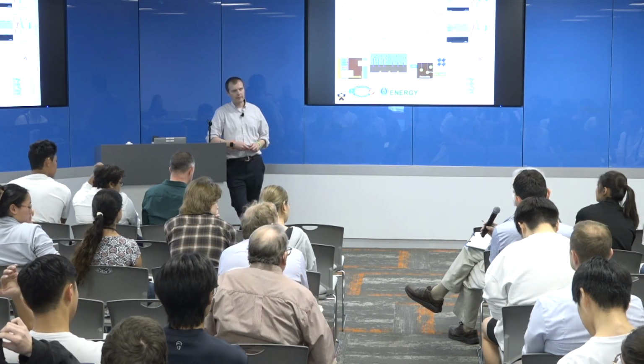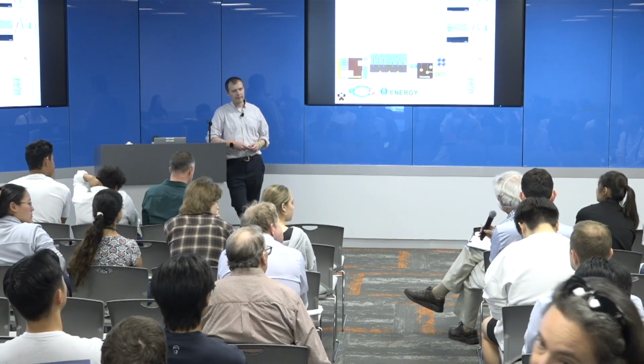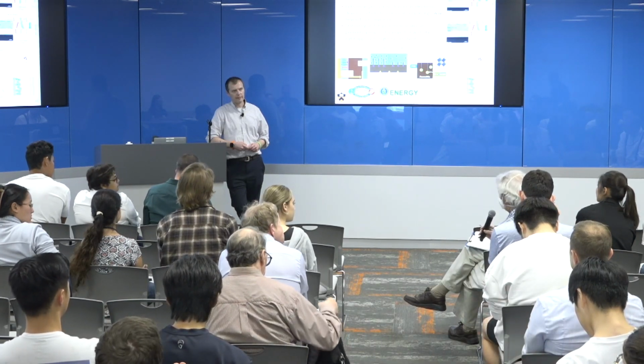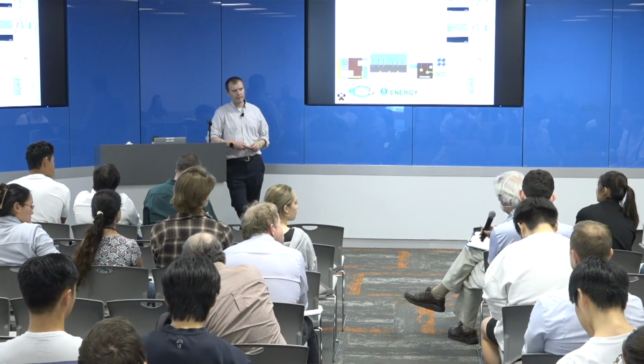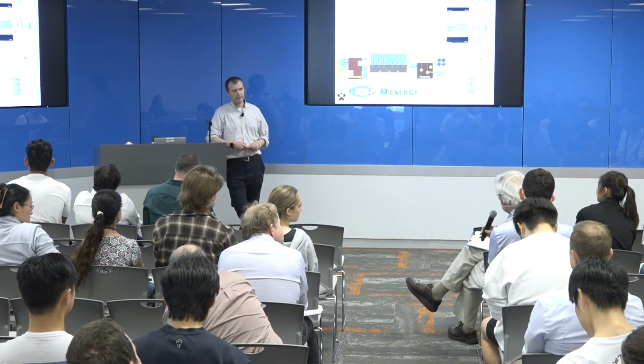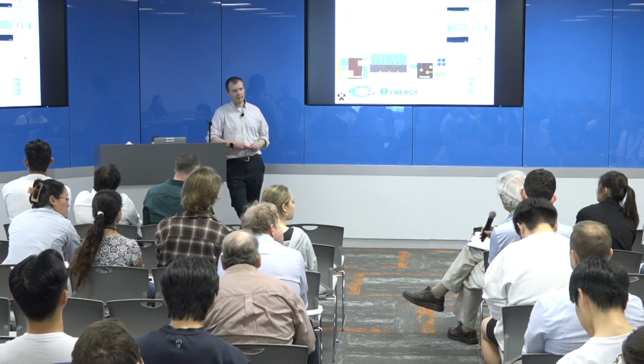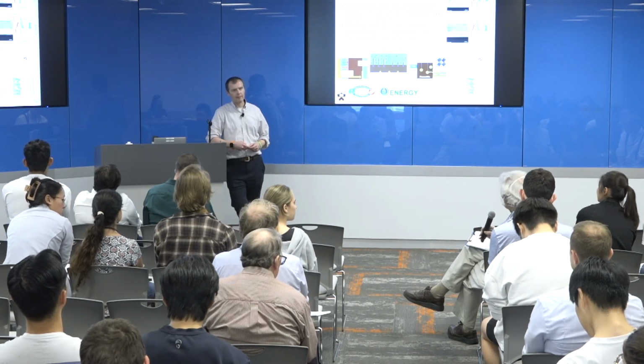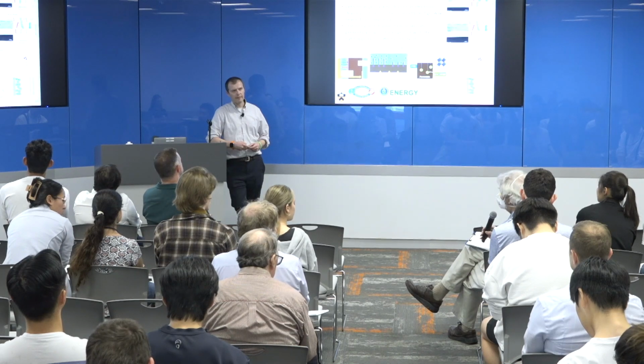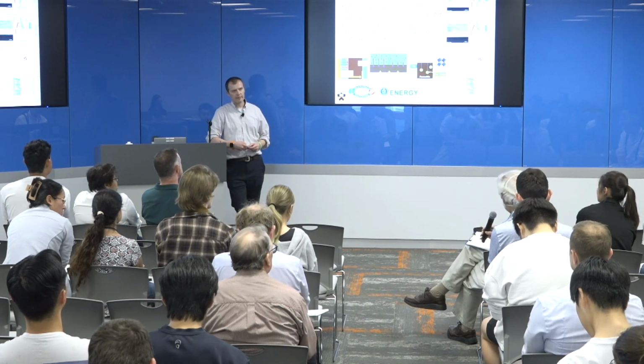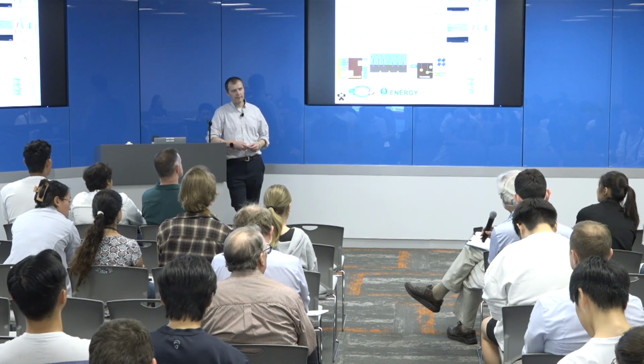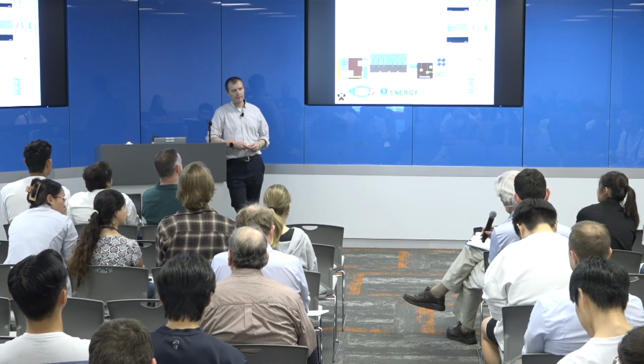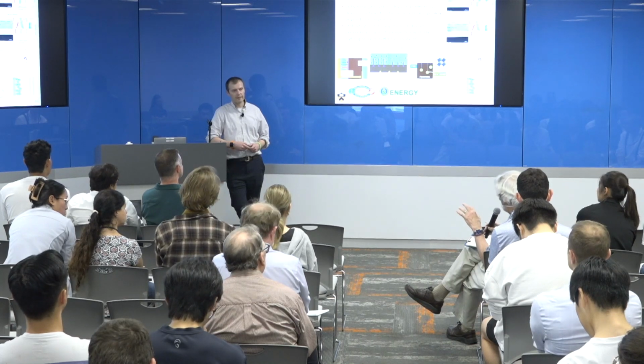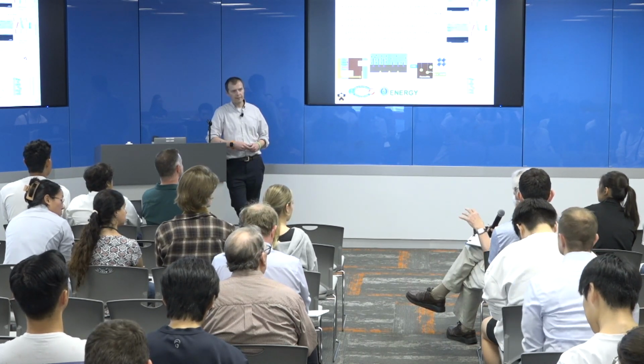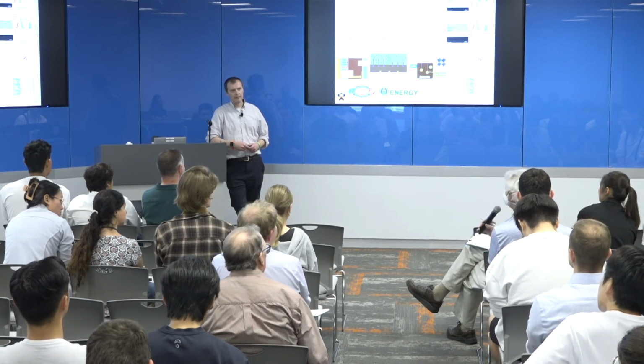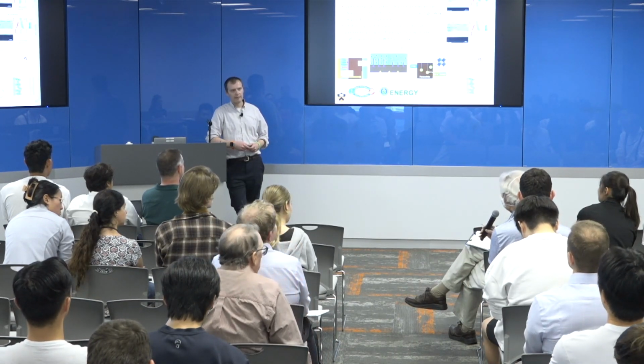And what that shows is that the iodine, in this case, binds with the anions at the anion sites and forms molecular interstitials. So your I3 minus is really an interstitial which is actually attached to a lattice ion. It's essentially split interstitials around a lattice site. Also, the system generates cation and anion vacancies.